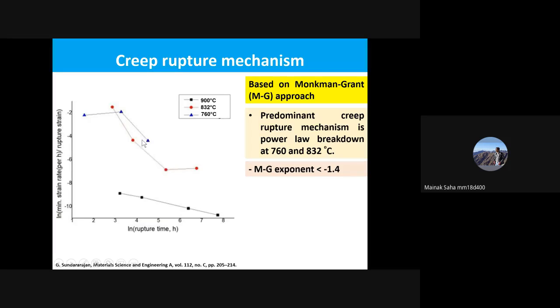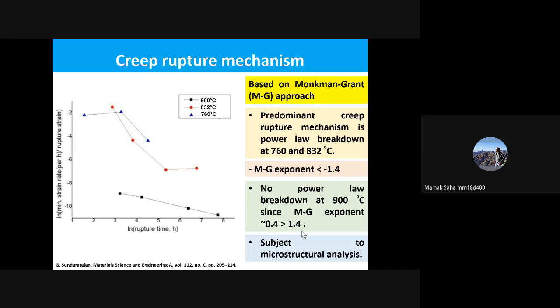The reason I say this is that the Monkman-Grant exponent, which can easily be extracted from this plot, is found to be less than minus 1.4 in both the 760 and 832 cases. In the second case, we see that there is no power law breakdown at 900 degrees, because the Monkman-Grant exponent is nearly equal to minus 0.4, and that is comparatively much greater than minus 1.4. I'm sorry, I have to put a negative sign here. So it is more than minus 1.4. So definitely we can now get an indication that there is a power law breakdown at the first two temperatures, 760 and 832, but no power law breakdown at 900. But again, this is also subject to further microstructural analysis.